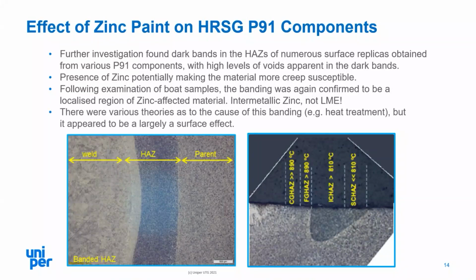Several theories were offered up as the potential cause of this banding, particularly the possible effect of heat treatment which had been applied to the welding. But what we saw was it was largely a surface effect. The particular example shown here in the grade 91 steel is between about 100 to 200 microns in depth. Where it's been observed in 2 chrome components, then typically it's perhaps been 1 millimetre or 2 millimetres deep. But all the concerns that we had were related to the grade 91 components.